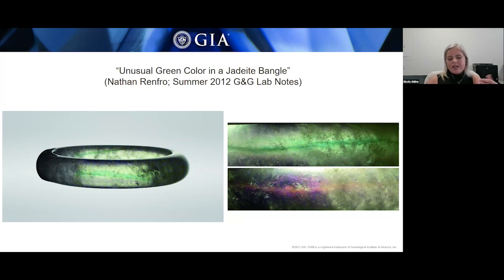And then under magnification, that green zone followed a textural zone that was much finer and denser than the other portions of this bangle. And there were no indications that this might have been repaired or that manufacturing could have been performed. But the green color actually proved to be a flash effect that was visible when the viewer's line of sight was parallel to that textural zone against the light background. And when that background was dark, that flash effect was an orange color, and you can see that in that bottom right photomicrograph. And so polymer impregnation was confirmed with the aid of FTIR spectroscopy to be present in this jadeite bangle.